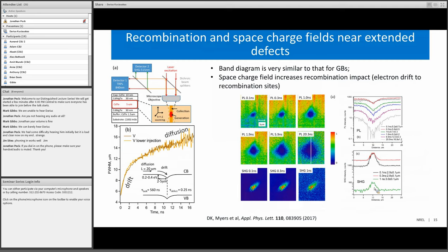So when this data is put together, we come up with the band diagram for the extended defect, which is very similar to the grain boundary diagram, in which we know both the amount of band bending and the extent of the band bending and the carrier diffusion length, and get a pretty complete description of recombination in this case.